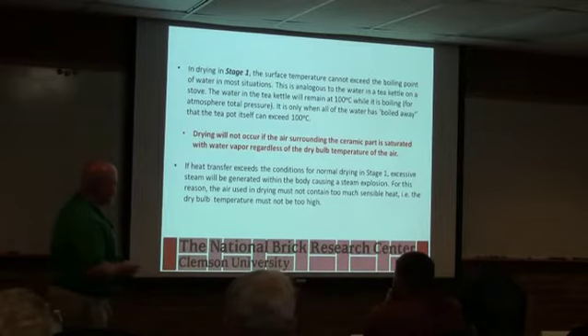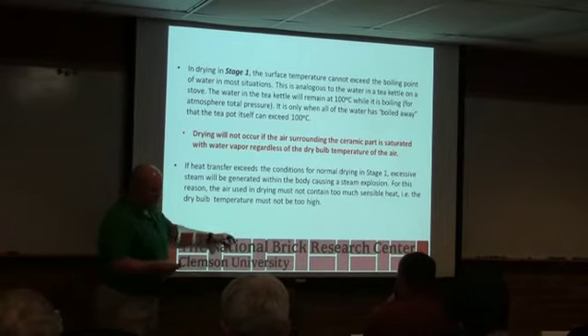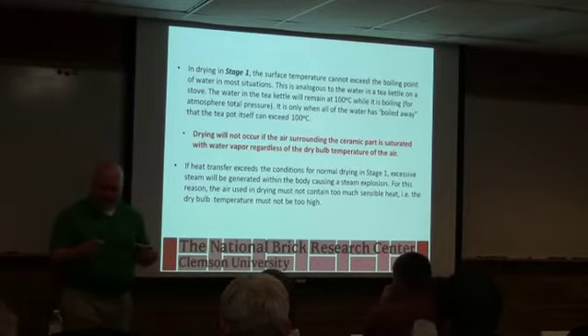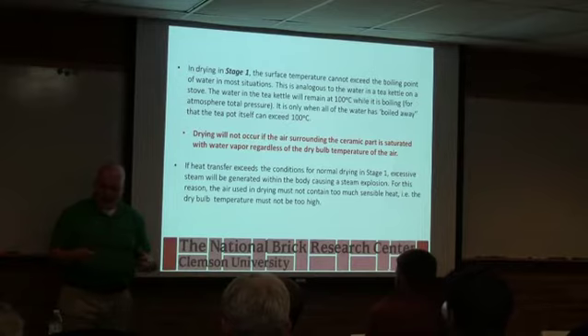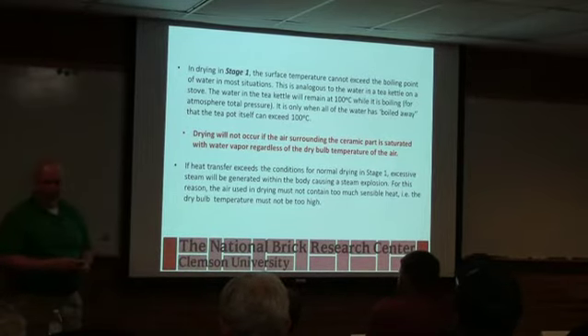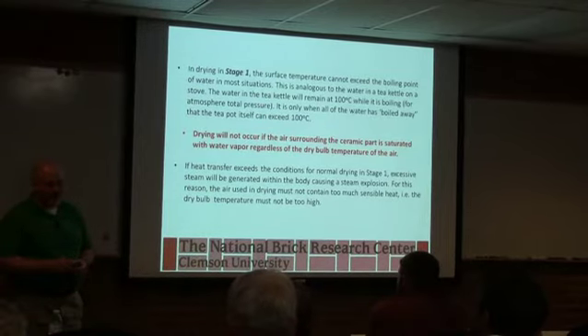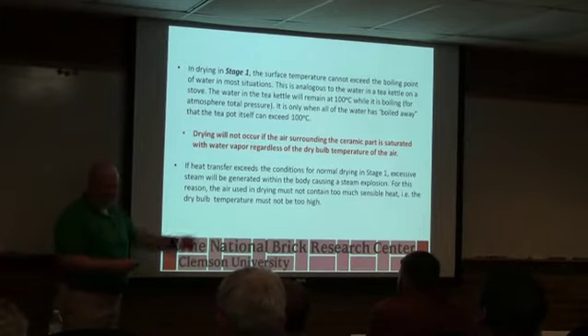It's exciting. So we used to do a test too. I don't know if you ever do this, where you wrap a brick up in foil and you put it in the dryer and you open it up and you see if it falls apart. We used to do that in the short course when Dr. Robinson was alive. And we'd have some brick that had very little clay, and it would just turn to sand when you'd open it up. It was amazing. I need to bring that test back.